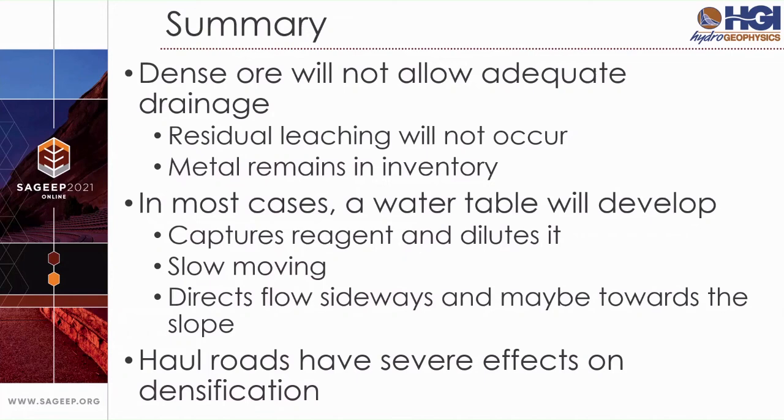In a second problem of densification, we have investigated the effects haulage equipment has on the leach pad. The cyclical and vibrational stresses cause compaction deep within the leach pad, as indicated by highly resistive ore surrounded by otherwise low resistivity wet ore. These haul roads can have high economic consequences, leaving behind a significant amount of metal that can add up to tens of millions of dollars. Thank you.